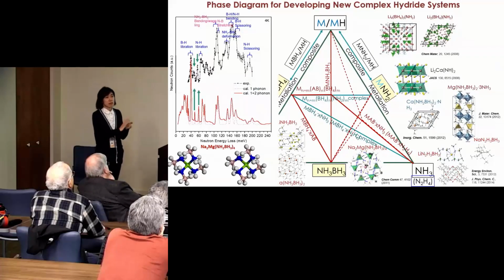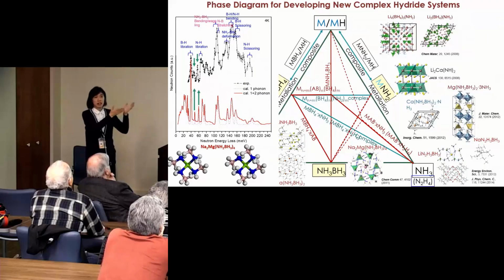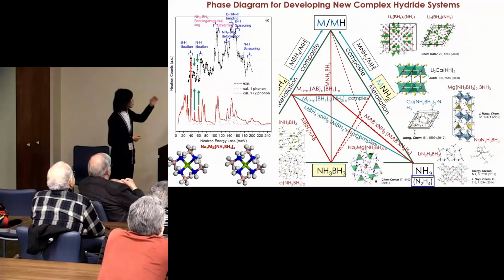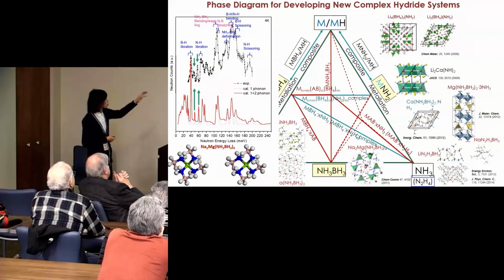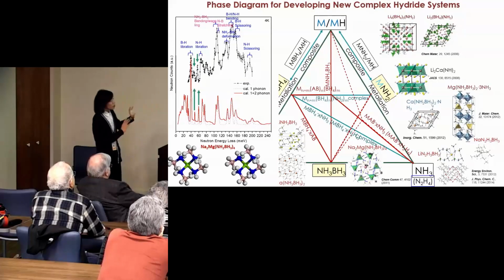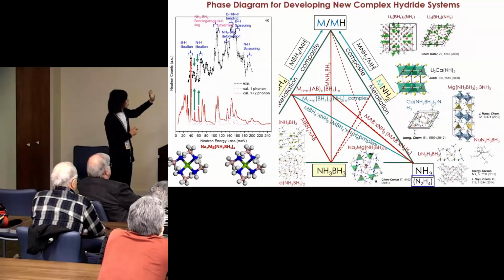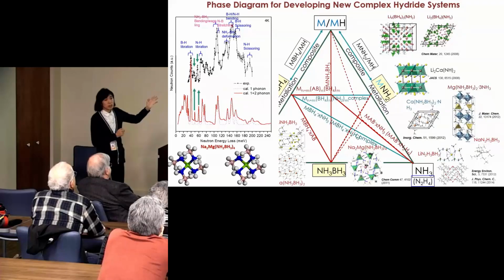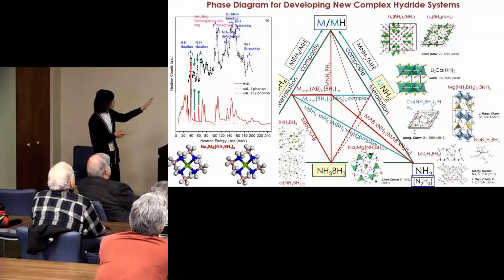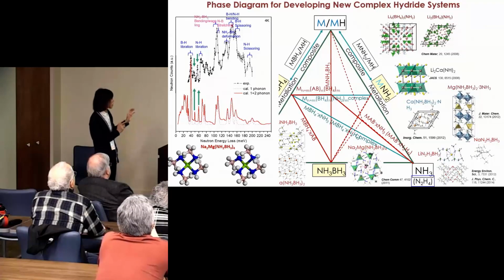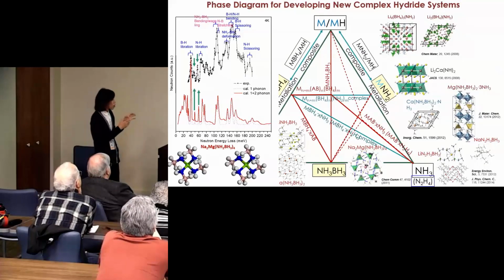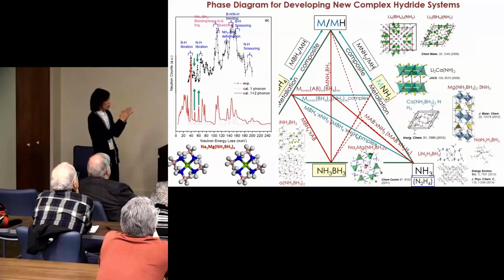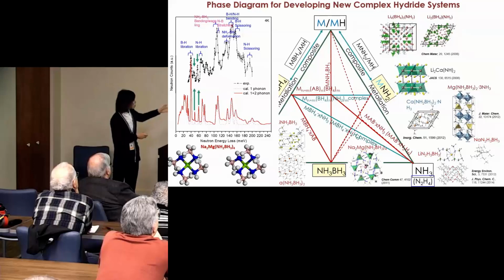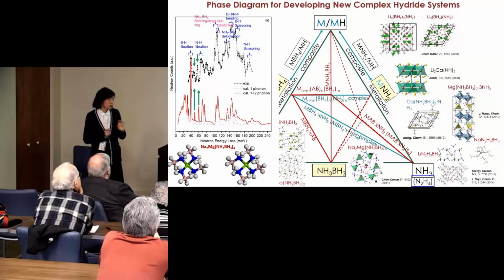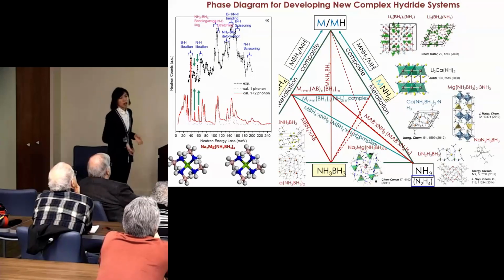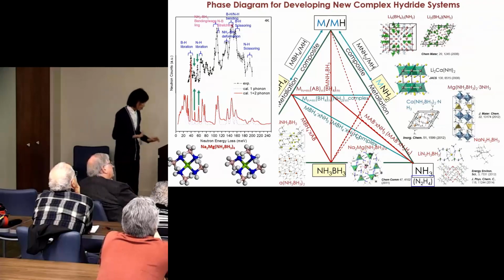So sometimes I collect the neutron vibration spectrum and calculate the phonon density of states and compare them to see how they agree with each other. Here is an example of neutron vibration data collected on sodium magnesium amidoborane. You can see the observed spectrum and the calculated spectrum. They actually show fairly good agreement, and especially, the neutron vibration spectrum can pick up some signature phonon modes, which correspond to some characteristic structural features. For example, in this system, from the determined structure, we found magnesium will only interact with the nitrogen end of the amidoborane. And indeed, we observed the stretching and bending modes between the magnesium and nitrogen. So this just provides some indirect evidence for the structure we determined.